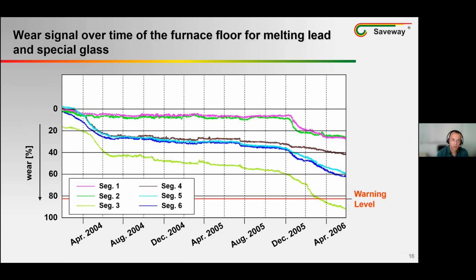The system will continually record the remaining wall thickness of the furnace lining, which can be called up and viewed at any time. In this way, the history of the furnace lining during the melting process can be clearly displayed. From left to right, you can clearly see an increasing wear of the lining.